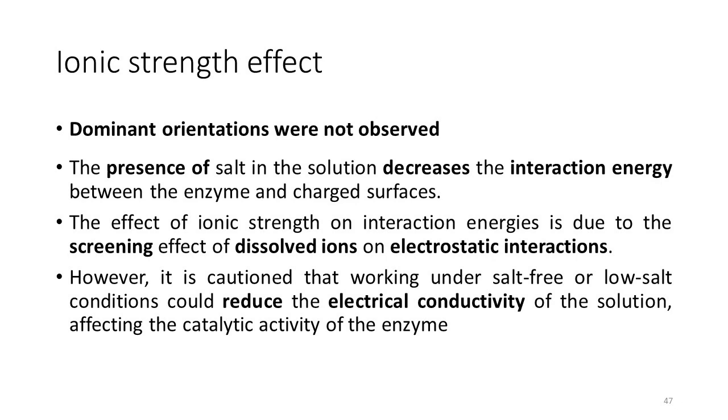Another problem is that if I have an electrochemical device, I'm probably going to need salts to have some electrical conductivity in the solution. In that way I can maintain the flux of electrons from the electrode to the enzyme. So that's going to be a problem for future experiments: while the salts hinder the adsorption of the protein, the salts are necessary to maintain a functional hydrogenase on the surface of the electrode. So it's one of the things that I would like to mention from the results that I observed during my thesis.